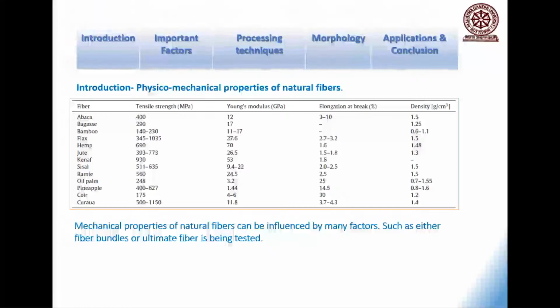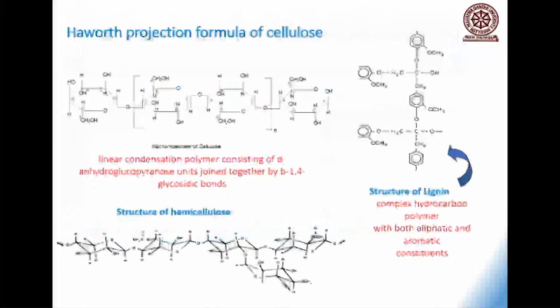If you look at the mechanical strength of this material, they are pretty good. I have shown the Young's modulus, the strength, elongation at break, how much you can stretch it. Look at the density. Density varies from 1.1 to 1.6, much lighter than glass fibers. Therefore, the specific properties are very good: property divided by density, because density is very low.